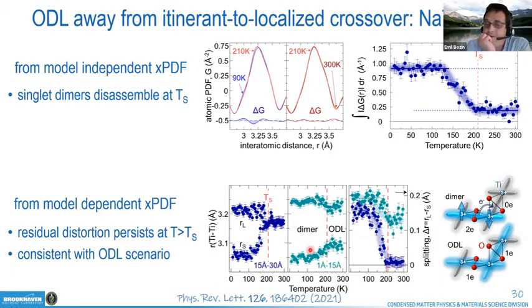So the other challenge is, of course, that you would have to come up with some kind of a mechanism of averaging out to the high temperature, high symmetry structure, which in case of spinels is relatively easy to comprehend, because you have a pyrochlore sublattice that extends in 3 dimensions, and so these objects randomize and end up into an average undistorted pyrochlore tetrahedral network.